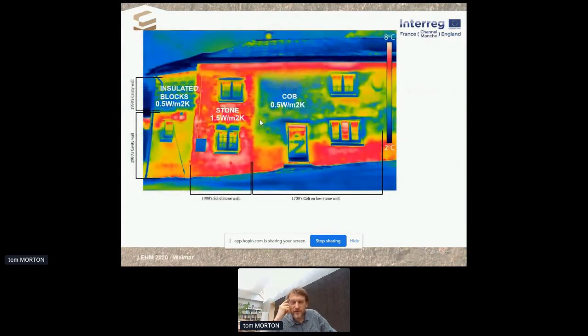In this image, and this goes back to some of the points Peter was making, this is a thermal image of a building that's got different kinds of construction from different periods. And the cob, the 300-year-old cob wall on the right, achieves a U value of about 0.5. So this is performance in a live building, as it were. Better than the stone wall that dates from 100 years ago, and the brick cavity wall from the 1960s. And it's comparable with the insulated concrete block wall from the 1990s. But the point is that none of these meet current standards, and they're going to become less and less so for future standards.